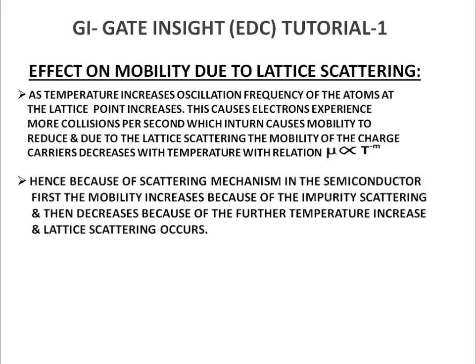Hence, because of the scattering mechanisms in the semiconductor, first the mobility increases because of the impurity scattering, and then decreases because of the further temperature increase when lattice scattering occurs. We can understand from this discussion that first, due to impurity scattering, the mobility increases. Then, because of more temperature increase, there are oscillations in the atoms, and because of that there is lattice scattering, and because of that the mobility decreases. In the impurity scattering we have the relation mu is proportional to T to the power of M, and in the lattice scattering we have the relation mu is proportional to T to the power of minus M.